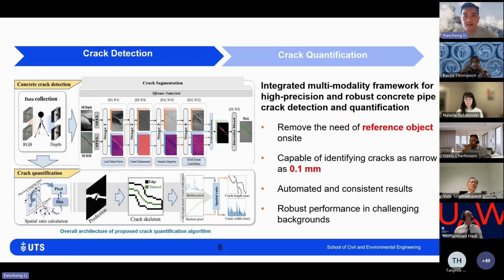So this is the main framework of our algorithm. We're using a multimodality framework for high precision pipe crack detection and quantification. We use two inputs. The first, as normally done for deep learning crack detection, is RGB data, the image we normally have from our phone or camera. The other modality is depth information, which refers to the distance from the camera to the concrete surface. It produces an image similar to the RGB image, but each pixel holds the distance from the camera to the concrete surface, so you have a whole map of the depth.